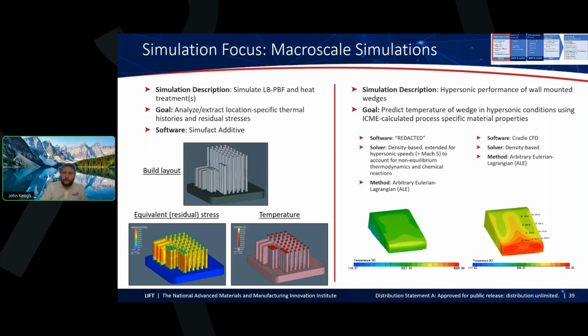And then looking at the macro scale level simulations here, what we're really talking about is the powder bed fusion and also hypersonic. On the left, we're simulating the powder bed fusion and heat treatment. So it's effectively a thermal FEA type simulation coupled in with our phase field and CALPHAD codes. The goal there was really to extract location-specific thermal histories and residual stresses. And one thing I didn't mention earlier about MIDAS is that it doesn't just pass models back and forth. There's a web and thread of connectivity across all those models tied to the geometry. So we can define a matrix of locations on a part and track them from code to code to code. We have this point tracking capability that we can carry all the way through, so we can audit on a location-specific basis. We can predict residual stress and temperature and align that against our physical results.